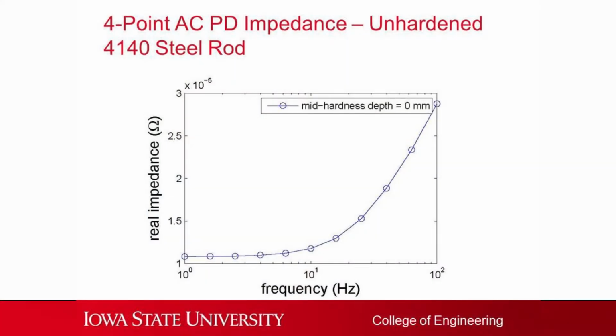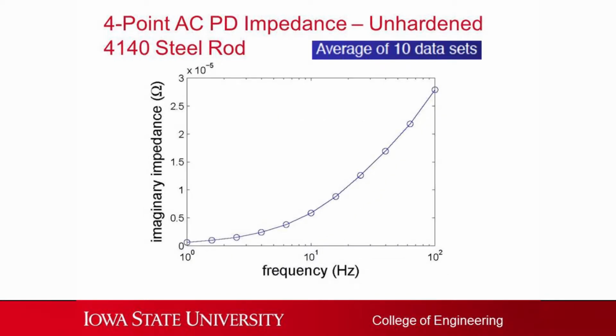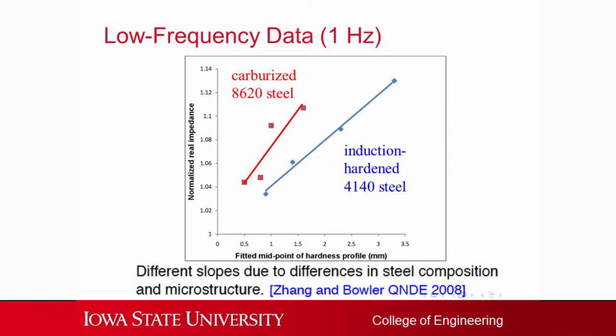So we took our 4-point probe and we did some measurements on these materials, a couple different steels. And so what we found then is that these two types were hardened in different ways. This is essentially our 4-point probe measurement, and this is the midpoint of the destructively measured hardness. And we can get a correlation between the two. So there is a potential that we could replace that long-winded analysis with a quick NDE measurement.